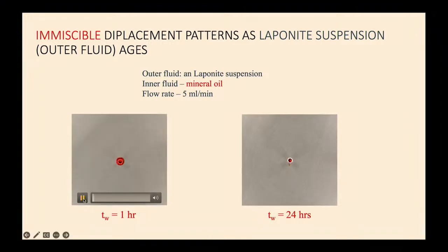Okay, initially nothing. This is almost like a viscous displacement. So you have this interface, a stable interface that grows, and now you can see that there are some tiny protrusions that are beginning to develop. So after that initial stable growth, you see some fat protrusions that develop. We call this the flower pattern. And one thing you would notice is it's taking forever to propagate. That is because of the stabilizing effect of surface tension. So we call this the flower pattern.